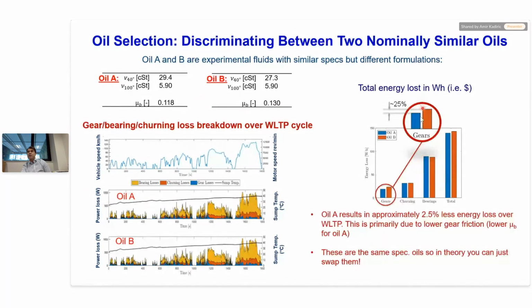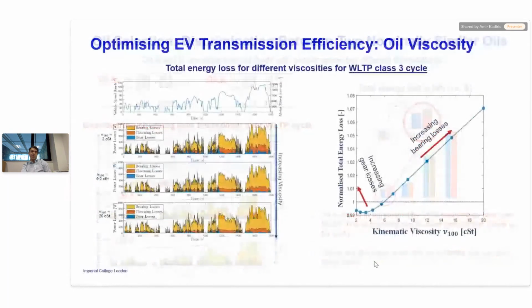The biggest difference is in gear losses. Remember, gears operate in mixed lubrication, so it's the boundary friction that made a difference. If you did a third formulation that reduced the bearing losses, you could probably do even better. But in this particular case, between these two oils, we were quite pleased to be able to see a difference, even though they're the same spec oil, so you could just swap them directly.